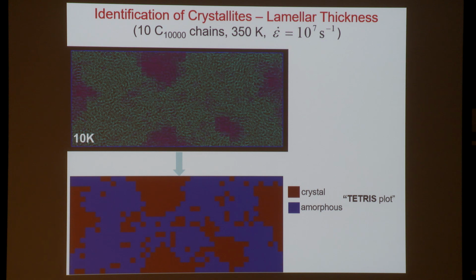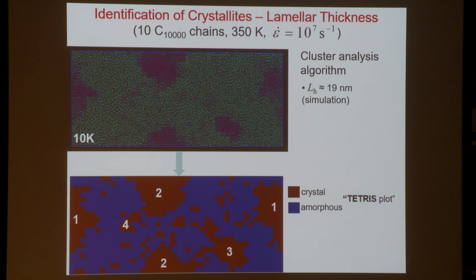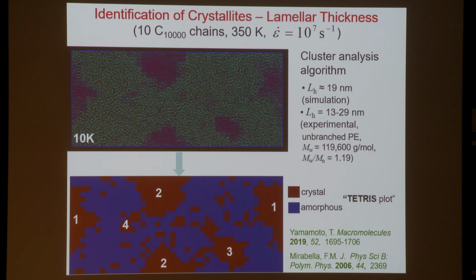From this, with Yamamoto's criterion, we take an atomistic structure and we convert it to what we call the Tetris plot. That is, we have crystalline and amorphous regions only in the system. And then we conduct a clustering analysis. For example, for this kind of configuration, one identifies 4 such clusters. And for each cluster, one can calculate the dimensions that it has. The cluster analysis indicates a dimension for the finished semicrystalline morphology of roughly 19 nanometers, which is not too far from what experimentalists report, but for polyethylenes that have been crystallized under quiescent conditions.